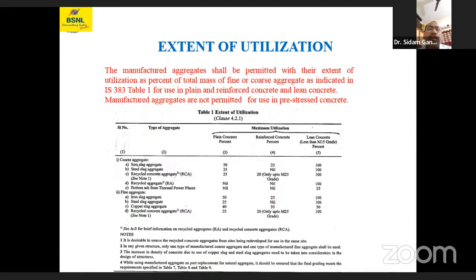Next, extent of utilization. Here, there are fine and coarse aggregates. In coarse aggregate, iron slag, steel slag, recycled concrete aggregate, and recycled aggregate. These are the coarse aggregates. Here, coarse iron slag in plain concrete, 50% is allowed, and in reinforced concrete, 25%. For lean concrete, we can use up to 100% iron slag.